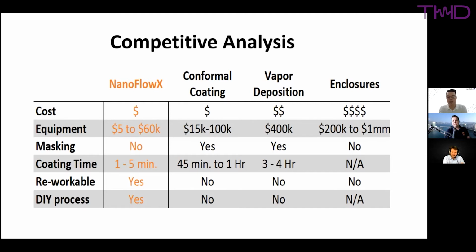Oh, so what you mean, there's actually enough conductivity through the coating? Yes, there is. It's funny, and a good example, we coated a PoE camera for a large electronics manufacturer. And we gave them a little bit of solution when we returned the device and told them, hey, make sure you coat your RJ45 because they're going to plug it in and power it up. Well, they forgot to do that, and they threw the camera in water. And 15 minutes later, during their test, the feedback burned their $1,200 switch. When you coat one side of the device, you have to coat the other side. You can't have a finished product if one half of it's not treated.